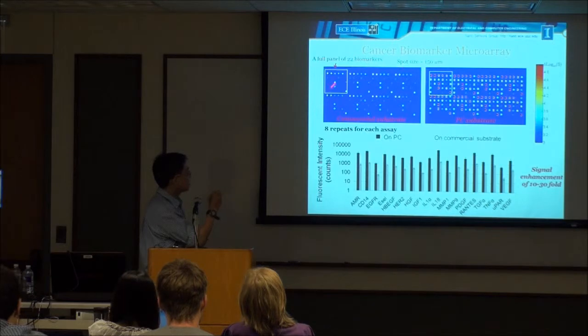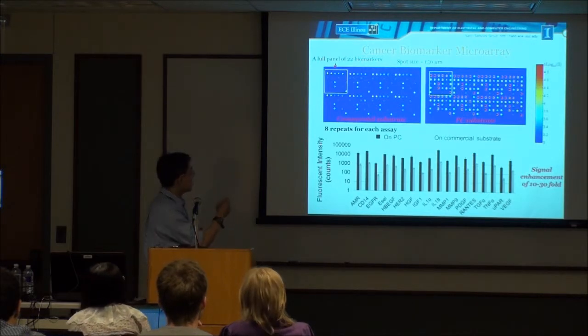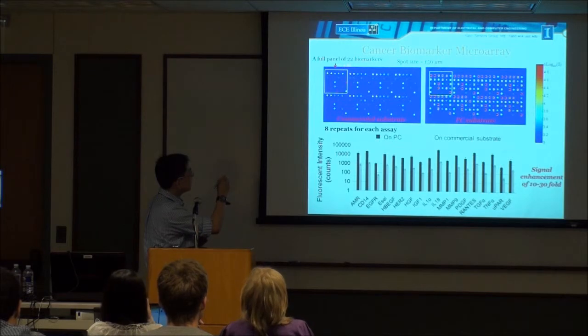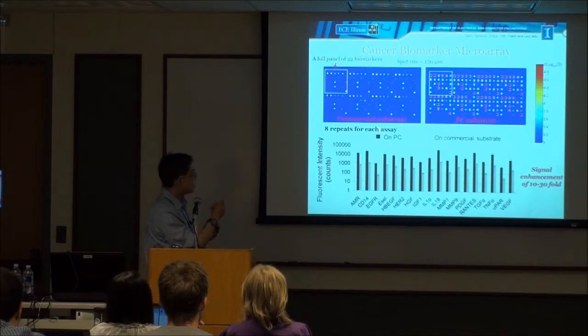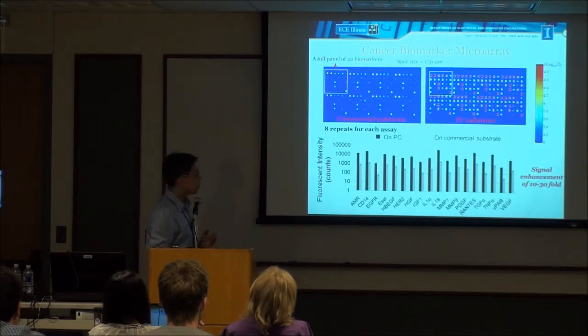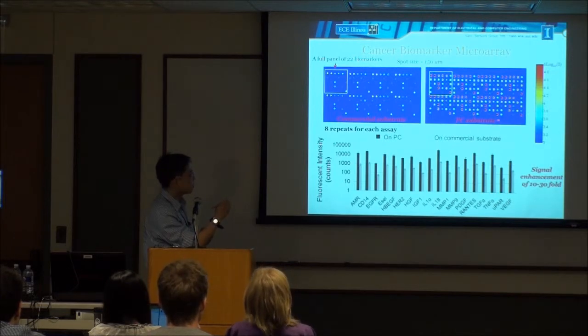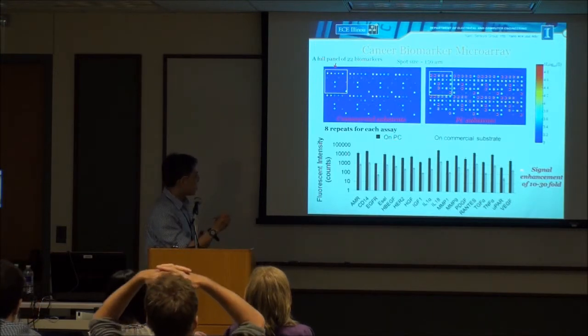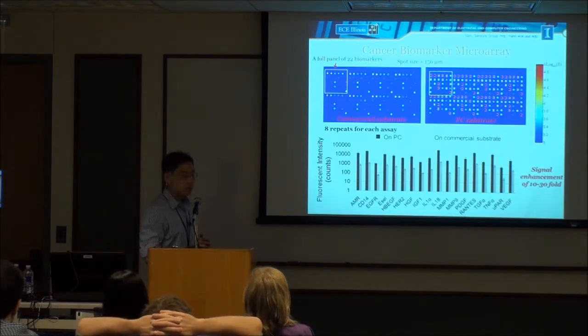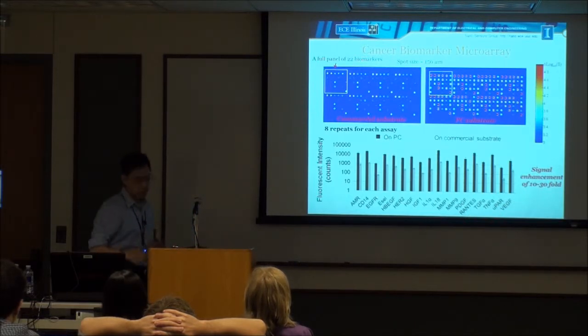When we look at the results, the left image shows the fluorescence image from a commercial substrate. Each sub-block contains a panel of 22 biomarkers, and each of those 22 biomarkers is repeated 8 times. Eventually, the signal intensity is averaged between the different repeats. The pseudo color represents the intensity of the emission. You can see that on the photonic crystal substrate, the fluorescence emission intensity is much stronger than on the commercial substrate. The bottom figure summarizes the fluorescence intensity versus different types of biomarker. On average, the enhancement factor is 10 to 30-fold.